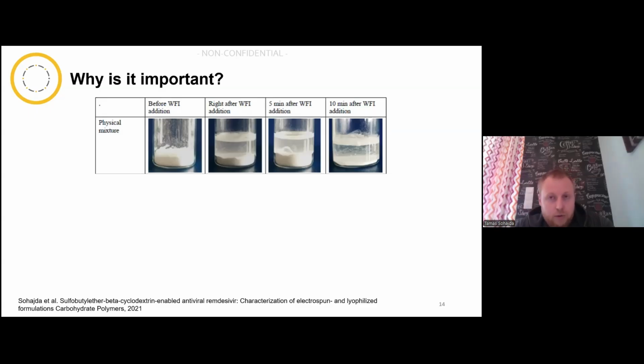So of course you can create a powder, but this powder doesn't get dissolved. The cyclodextrin part gets dissolved. This is what you see, but the active ingredient doesn't get dissolved at all. And that's because in a physical mixing, complex formation doesn't occur, or only to a very little extent, depending on what kind of procedure you use. So the API doesn't get into the cavity of the cyclodextrin, and accordingly its properties are not matched, so it doesn't become water soluble.